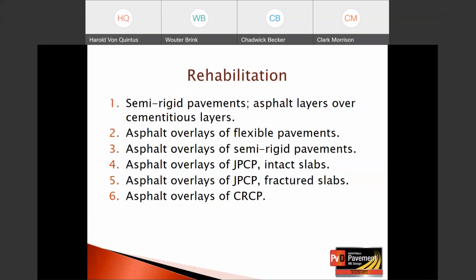cracking are listed on this slide. There are semi-rigid pavements, where there's asphalt layers over a cementitious or a cement stabilized layer. And reflection cracking does apply, and that's for a new semi-rigid pavement. We have asphalt overlays, flexible pavements, asphalt overlays of semi-rigid, asphalt overlays of intact jointed plain concrete, asphalt overlays of fractured jointed plain concrete pavements, and then asphalt overlays of CRCP. Reflection cracking would be applicable to all of these different rehabilitation strategies.